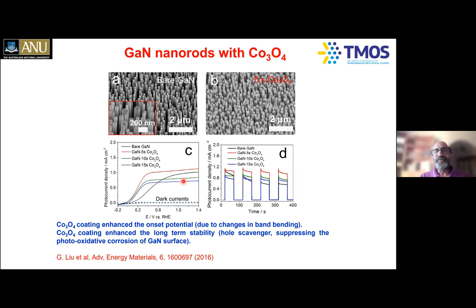But it turned out that even though gallium nitride is normally very difficult to etch, photo-oxidation corrosion takes place, and the nanowires are not very stable. This is the work of my former student, Dr. Reddy, and my young colleague, Dr. Liu. We coated the gallium nitride nanowires with cobalt oxide to stabilize them. The cobalt oxide acts as a co-catalyst and hole scavenger, and we were able to show that they are very good from the stability point of view. But gallium nitride is transparent to visible light, and only absorbs ultraviolet light. Now we're exploring indium phosphide and other semiconductors as well. As I mentioned, you need efficiency as well as stability, and of course cost as well.